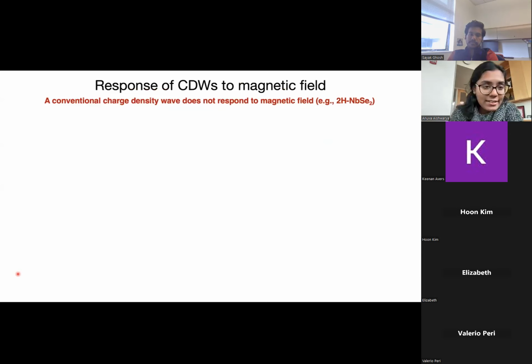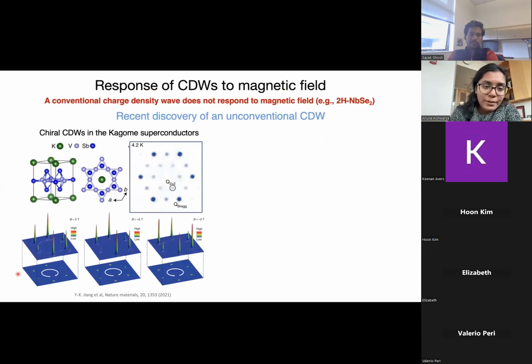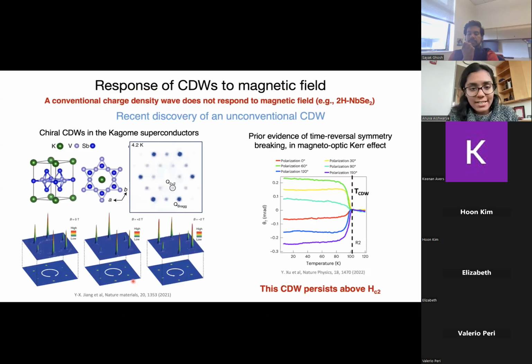However, in some recent studies on these Kagome superconductors, people have seen that the high temperature CDW actually responds to magnetic field in this strange fashion where you can flip the chirality of the CDW, which is shown here, by flipping the direction of the magnetic field. However, this is not similar to what we are seeing, because in this case, there's prior evidence of time reversal symmetry breaking in magneto-optic Kerr effect, and the CDW persists above HC2, which is different for us. For us, the CDW dies above HC2.